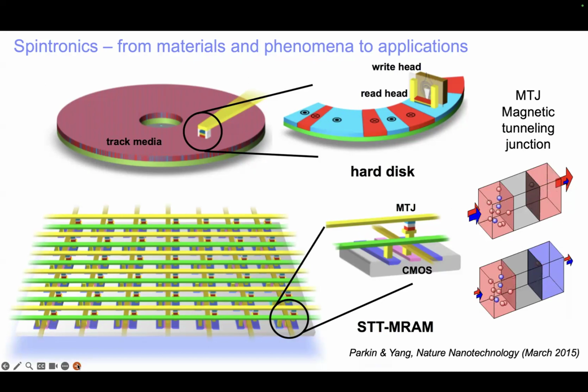And because the difference in the resistance of the device when, let's say, the rightmost electrode is pointing to the right or to the left, the change in resistance at room temperature can be several 100%. So it's very easy to detect the state of this memory device using a small current. So it's very energy efficient. At the same time, it turns out, and this is what I want to discuss next, you can write this device by simply passing a large spin polarized current through the device. This current, because it consists of electrons all polarized in the same direction, carries spin angular momentum that can be used to apply torques to the magnetization and can switch the magnetization from one direction to the other of the electrode that acts like the memory. And by design, we engineer the other magnetic electrode to be fixed in direction. This is the nature of MRAM.